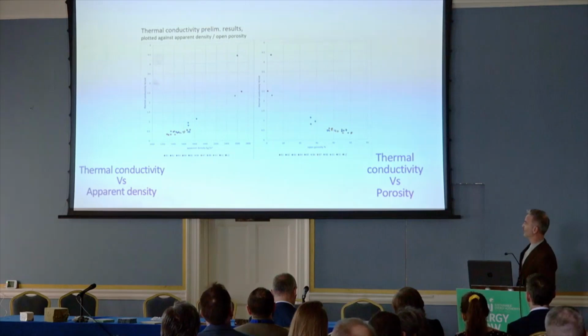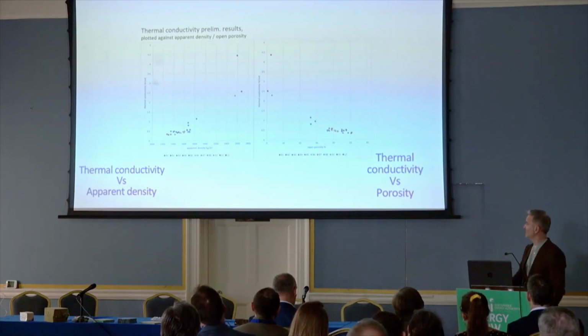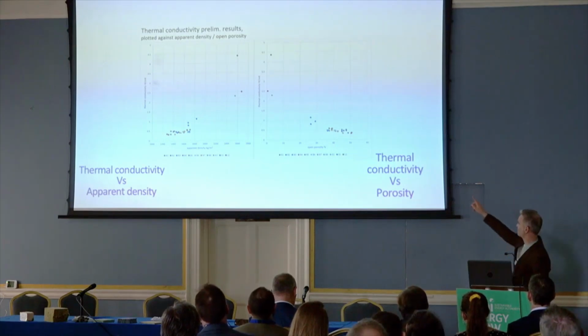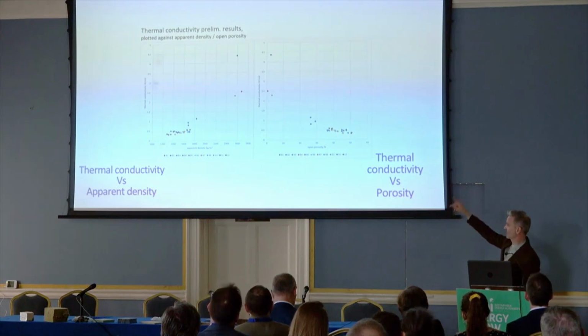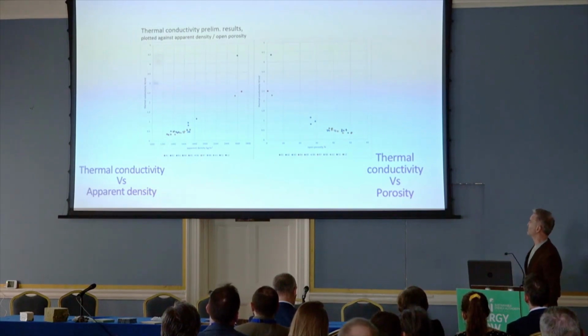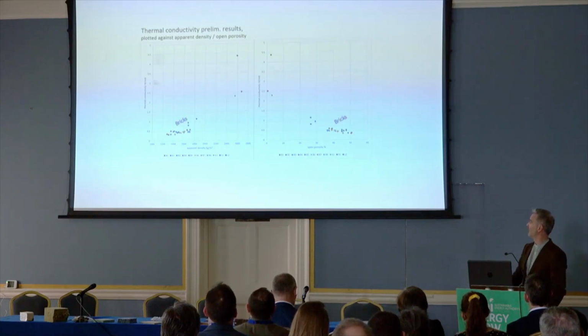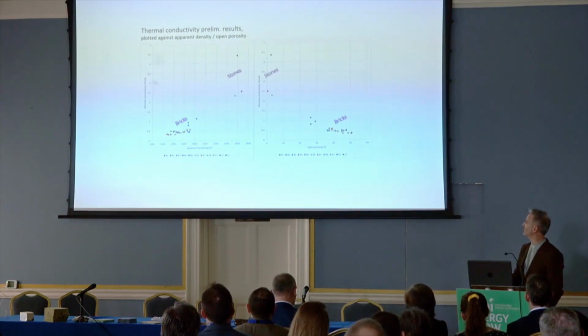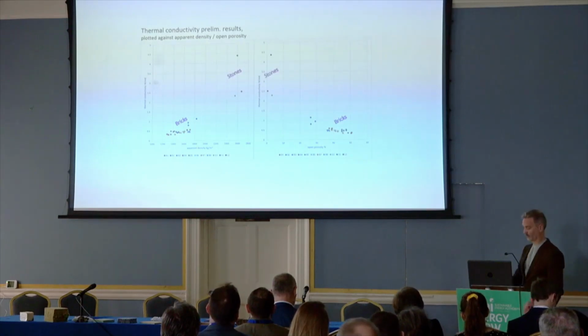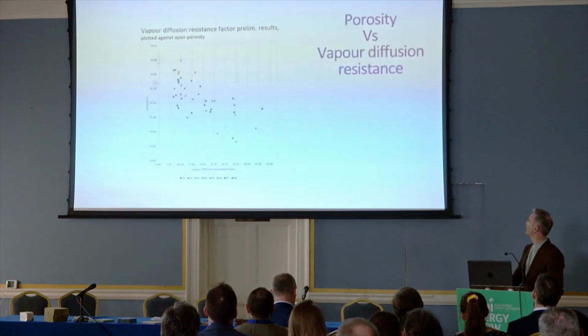Also, some maybe somewhat obvious results, but we see thermal conductivity increase as the density of the brick increases and decrease as the porosity of the brick increases. So thermal conductivity on the y-axis, density and porosity on the x-axis for both images. And of course, the bricks having a lower density have a much lower thermal conductivity than the stones, which have a much higher density, much greater thermal conductivity.